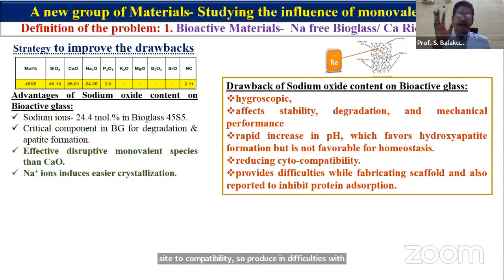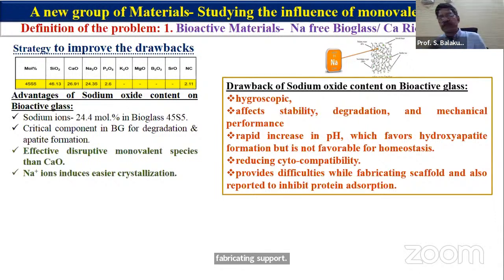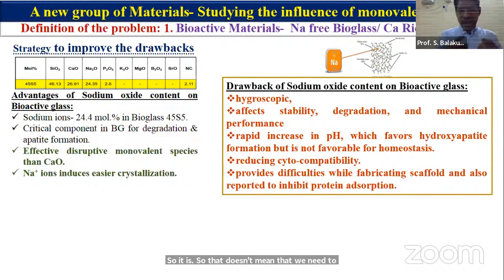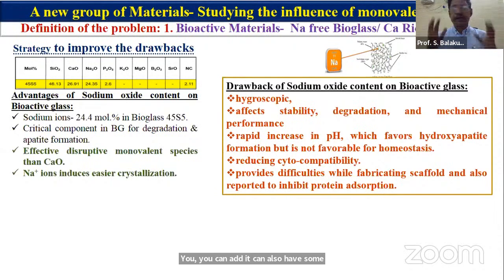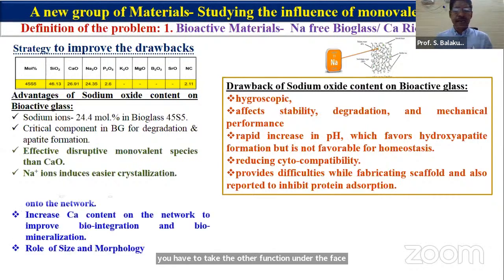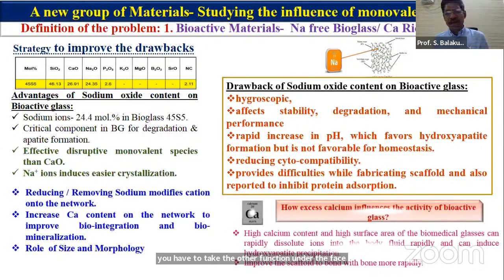That doesn't mean that we need to completely take out the sodium. You can also have some sodium, add other material, but the network connectivity should be around 3, and you also have to control the phase formation as well as your biocompatibility. So some trade-off should be there. That is what we have done in our work.